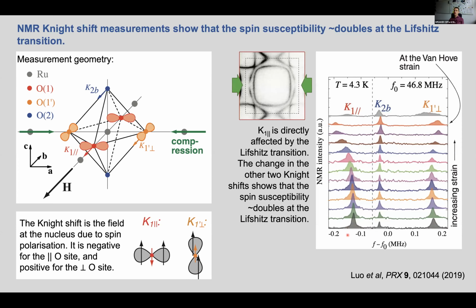Right, so this is what Stuart Brown's group sees as a function of applied strain. So these are our 3 oxygen peaks. This is the frequency shift. This is the NMR frequency shift. This one here is this parallel site with the negative Knight shift. This peak here is the perpendicular site with positive Knight shift.